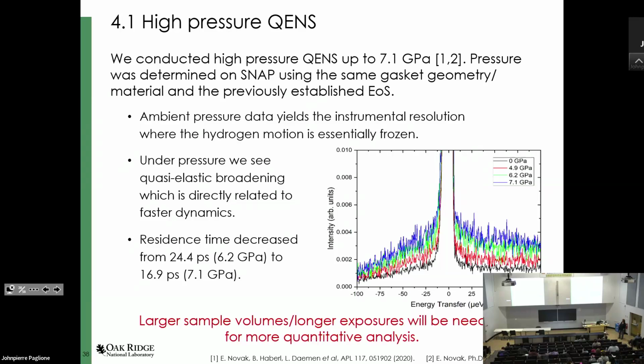But overall, we found that for real quantitative analysis, we wanted larger sample volumes or longer count times. So the QENS experts were sure they analyzed this correctly, but to really get the full information you can typically get from an experiment, yes. Other than what? How long did that take? We tried it again with 24-hour exposures, but then there was an issue with the source during that experiment.